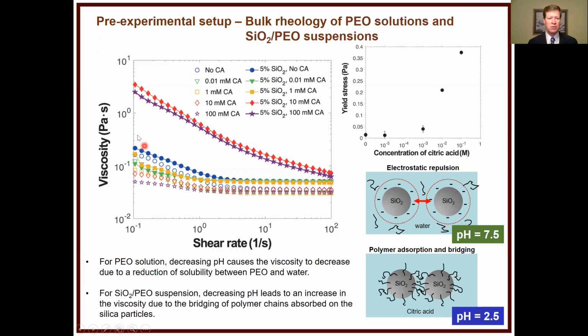And so this is what sets up this network that causes shear thinning, but more importantly, perhaps, is a yield stress that gets set up. After about a pH of maybe 4 and lower, you start seeing a dramatically high onset of yield stress. We can see this when we coat it. We can see this when we manipulate the fluids, but it's still certainly a relatively low yield stress. So you can think of still being able to coat these relatively freely.